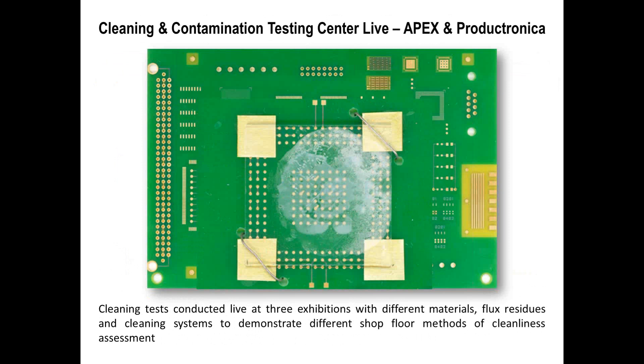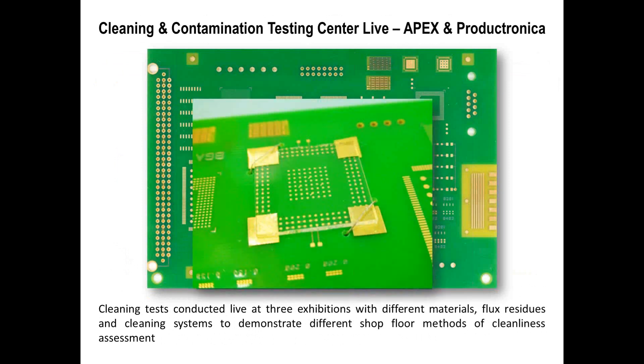As another alternative, you could print paste onto the exposed pads and reflow underneath the glass. You'll always have more flux residues left because it hasn't had the chance to vaporize off during reflow — but all that's doing is giving you more flux rather than less. Here's a sideways image of one of these boards after cleaning — there are no residues left behind, it's squeaky clean. Glass is quite a difficult surface to get absolutely squeaky clean.